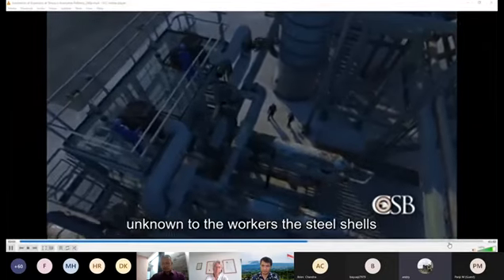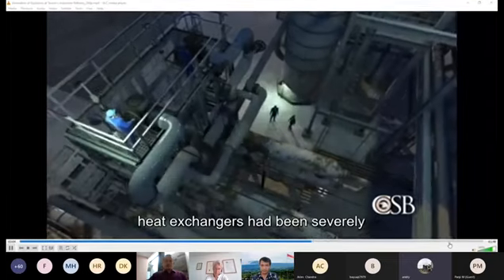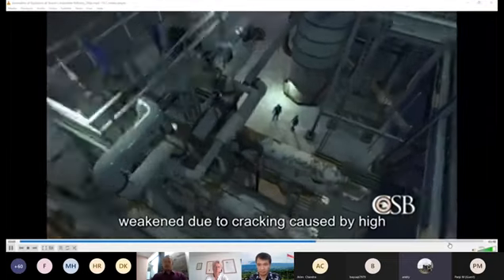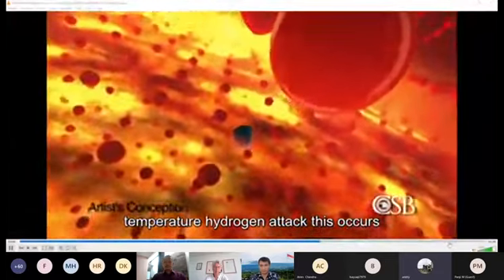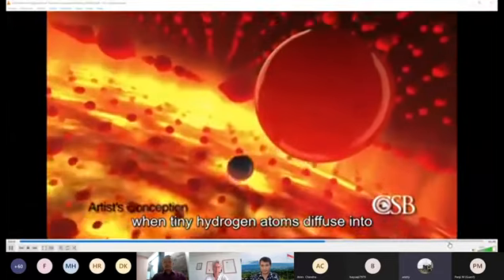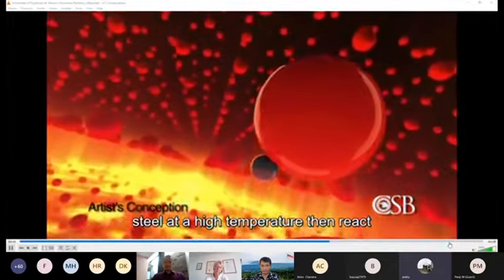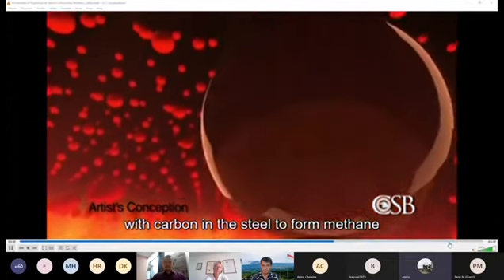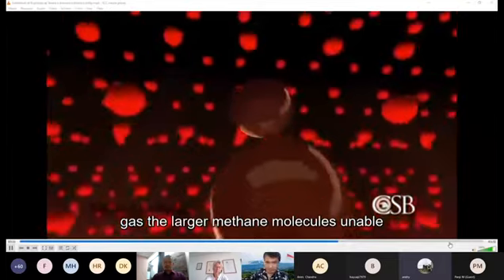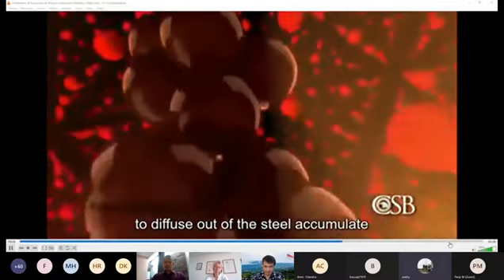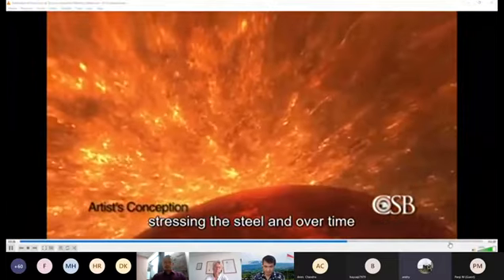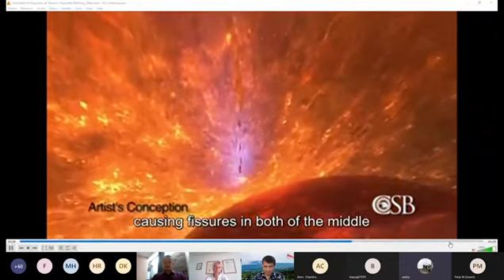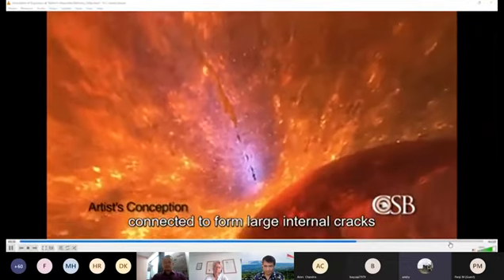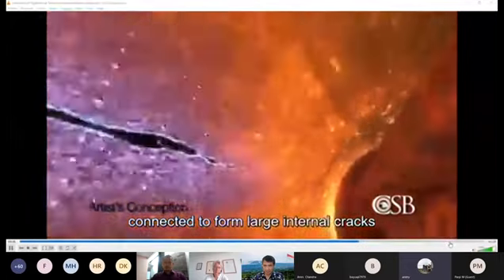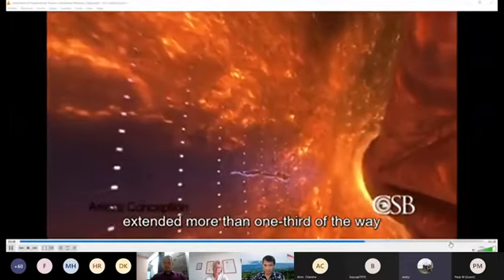But unknown to the workers, the steel shells of the middle vessels in both banks of heat exchangers had been severely weakened due to cracking caused by high-temperature hydrogen attack. This occurs when tiny hydrogen atoms diffuse into steel at a high temperature, then react with carbon in the steel to form methane gas. The larger methane molecules, unable to diffuse out of the steel, accumulate, stressing the steel and over time causing fissures. In both of the middle heat exchangers, the fissures grew and connected to form large internal cracks.